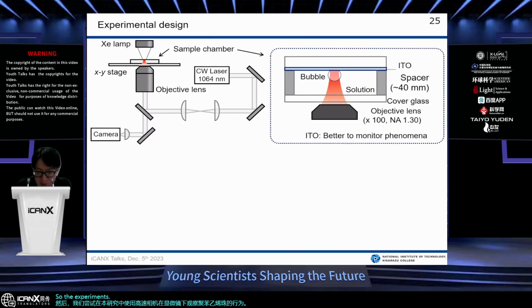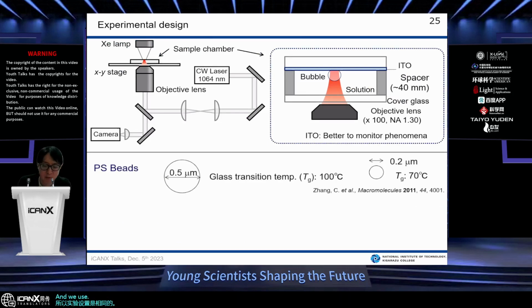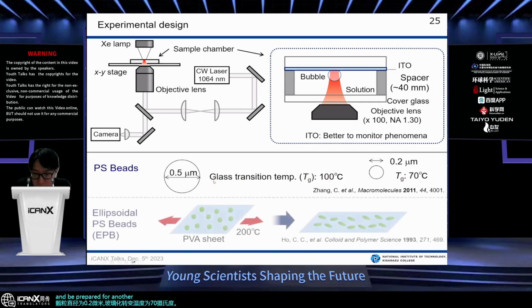The experiment setup is the same, and we use polystyrene beads. The diameter is 0.5 micrometer and the glass transition temperature is about 100 degrees Celsius, and another particle has a diameter of 0.2 micrometer and a glass transition temperature of 70 degrees Celsius. We prepared another sample, ellipsoidal polystyrene beads, abbreviated EPB. First, polystyrene beads are dispersed in a PVA sheet, then heated up and extended in one direction. So we made ellipsoidal polystyrene beads.